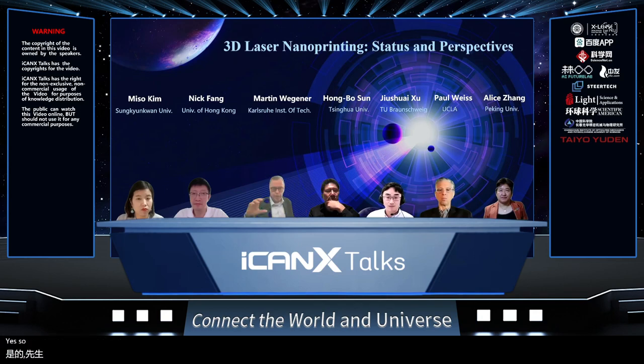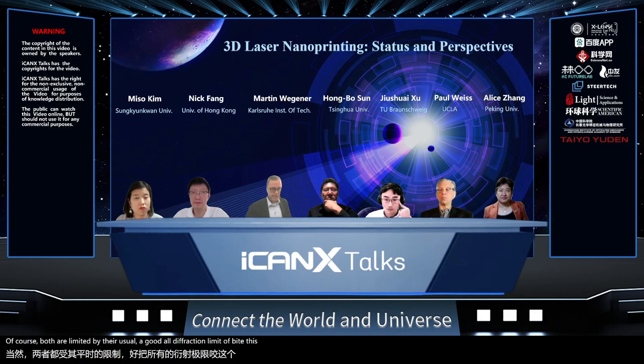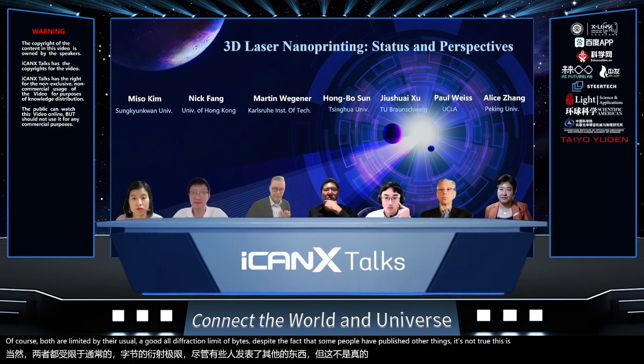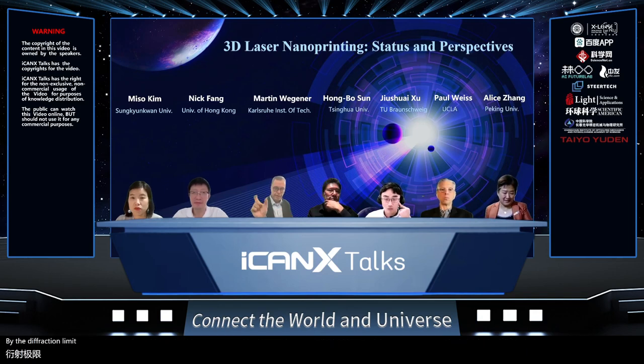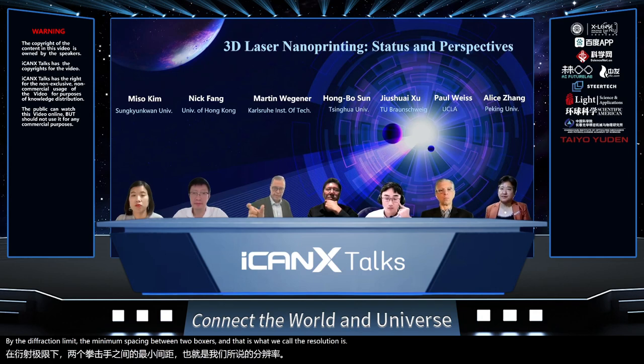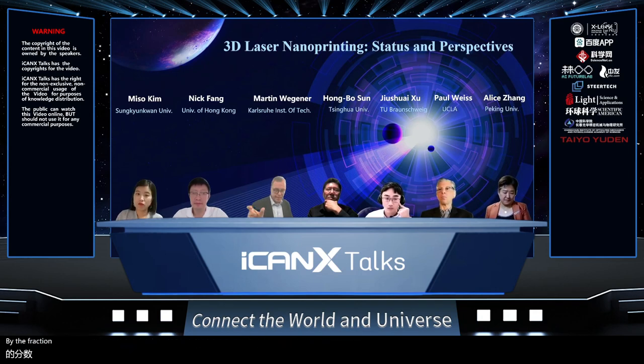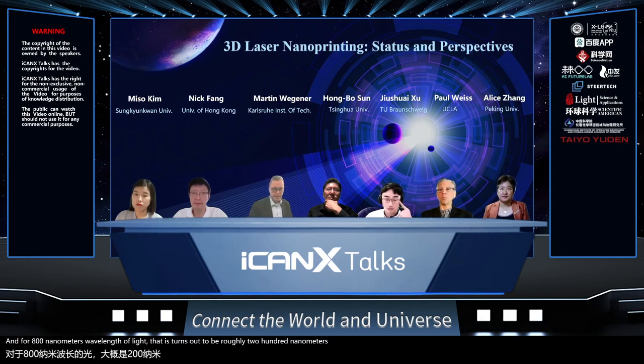Yes. So first of all, to the size of the voxel and the question of resolution. Of course, both are limited by the usual good old diffraction limit of light. Despite the fact that some people have published other things, it's not true. This is limited by the diffraction limit. The minimum spacing between two voxels, and that is what we call a resolution, is limited by diffraction. Technically speaking, it's limited by the two photon Sparrow criterion. And for 800 nanometers wavelength of light, that turns out to be roughly 200 nanometers. It scales with the wavelength.